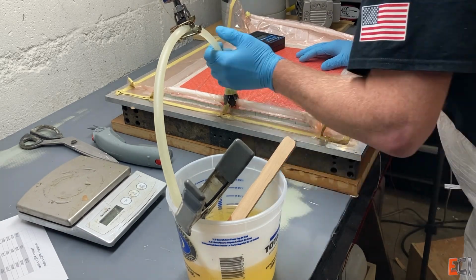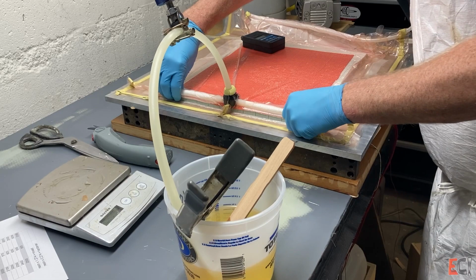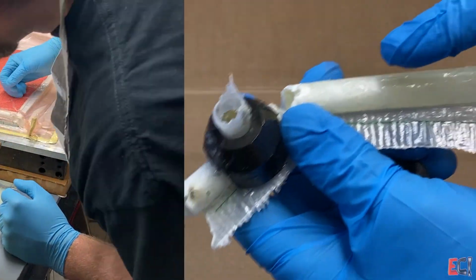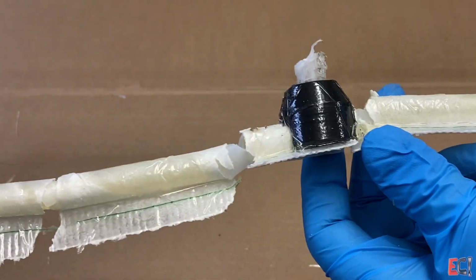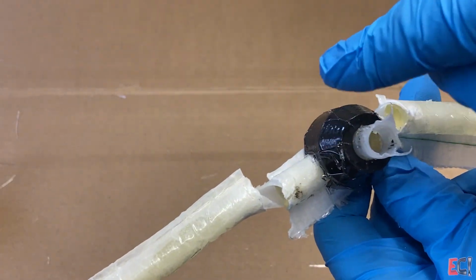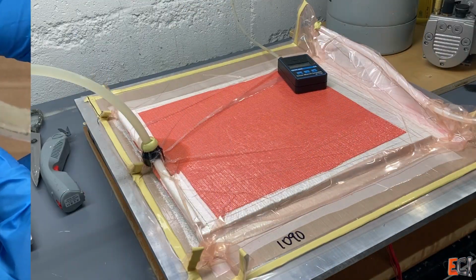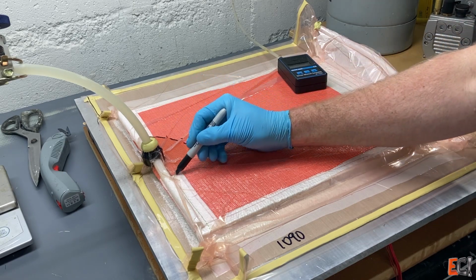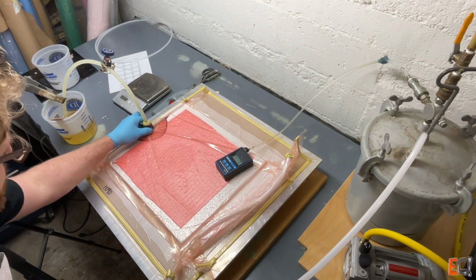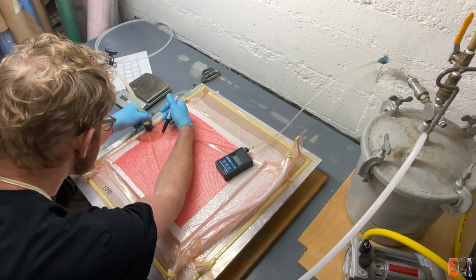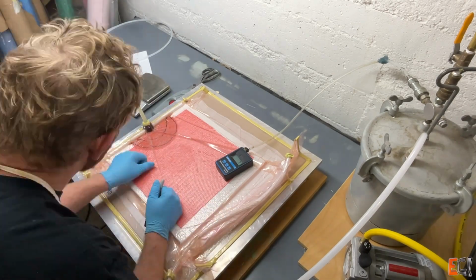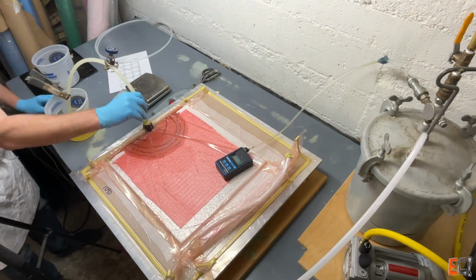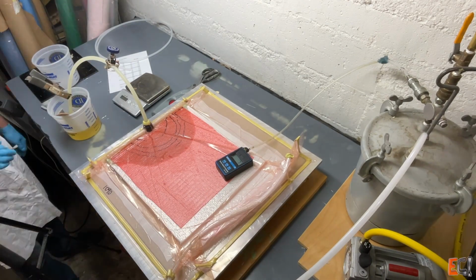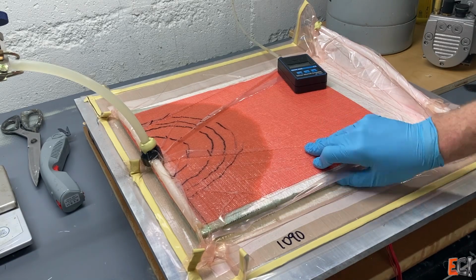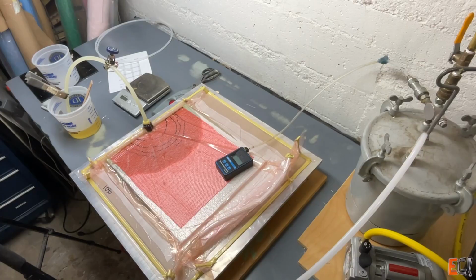Now, as I start this, I'm noticing that it's not filling the spiral wrap the way that I hoped. And you can look in here and see this bit I used is a special spiral wrap wrapped in a flow media. And it turns out I mistook the feed side for the resin side because I wasn't paying attention. And so I have something that is meant to block resin flow into that spiral wrap as it forms a vacuum perimeter. And I'm trying to use it as a flow feed feature, and it's just not letting the resin through. That product is a spiral wrap wrapped in peel ply and a perforated film to limit how much resin gets in when it's used on the other side of the infusion.